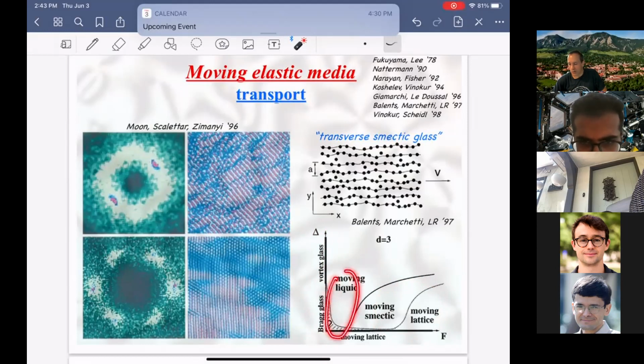Then what happens when you begin to try to depin it? We know the effects of disorder are very strong, so it really reshuffles. But the idea is that at very large drive, you average over disorder, so you get back to a crystalline state. That's at large velocity. But at intermediate velocity, something we can control by perturbing around the state, we can show that it's actually a state which has periodicity only in a direction perpendicular to the velocity.